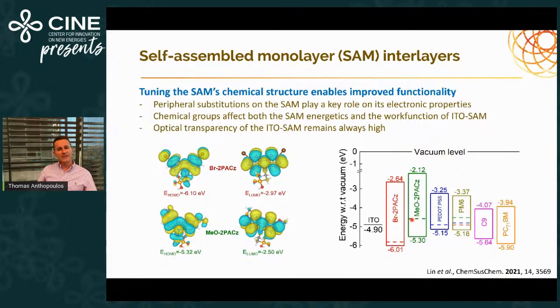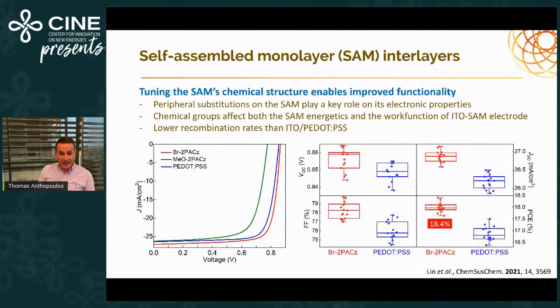Of course, this is just what we see with a Kelvin probe. We don't really know what happens when we create a bulk heterojunction-ITO SAM interface, because we have a number of pinning effects that, of course, play a major role in the overall electronic landscape across that interface. Nevertheless, the impact is dramatic. On one hand, we have PEDOT:PSS, which is heavily optimized and gives us very good efficiencies, typically 17.5%, some of the highest.